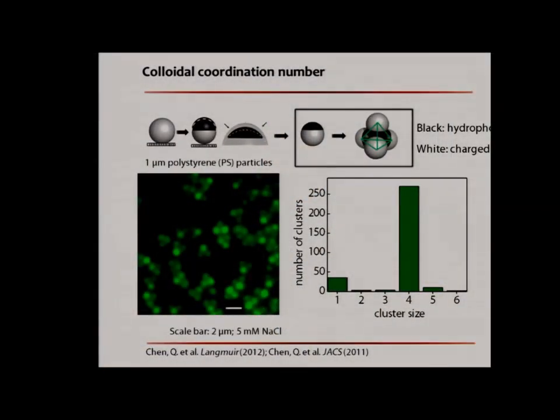The first experiment I did was to use Janus colloidal particles to demonstrate the coordination number concept. I made my Janus particles by starting from a monolayer of isotropic particles, having them directionally coated with gold, and then etching away the gold. In this method, I was able to control the size of the gold patch really accurately such that only 4 nearest neighbors are allowed.